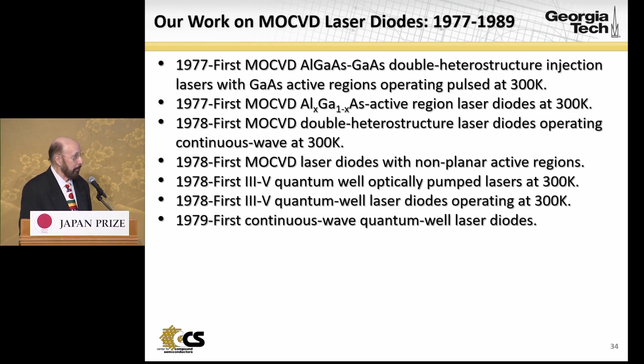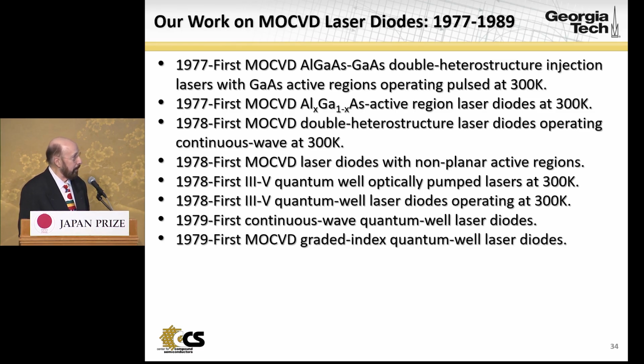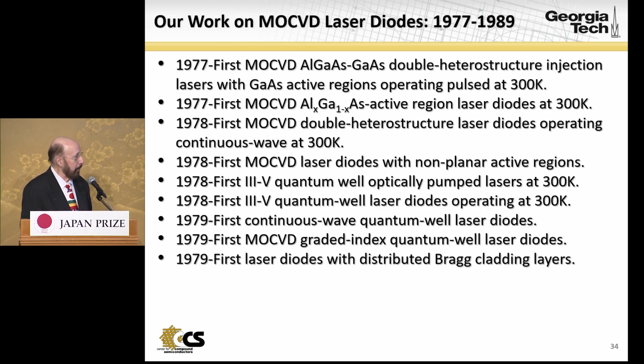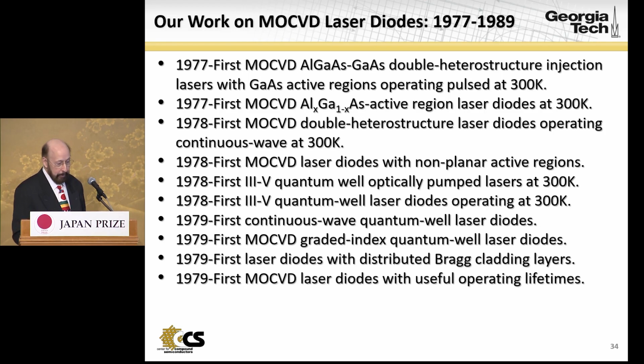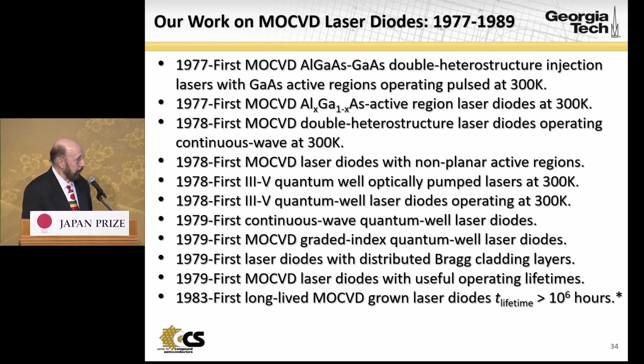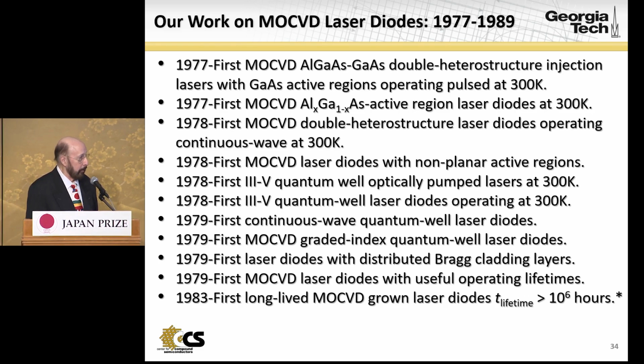First continuous wave quantum well laser diodes in 1979. First graded index quantum well laser diodes. First laser diodes with distributed Bragg cladding layers. First MOCVD lasers with useful operating lifetimes. And when I joined Bell Laboratories, eventually we, in 1983, demonstrated the first long-lived MOCVD-grown laser diodes with lifetimes greater than 10 to the 6 hours.